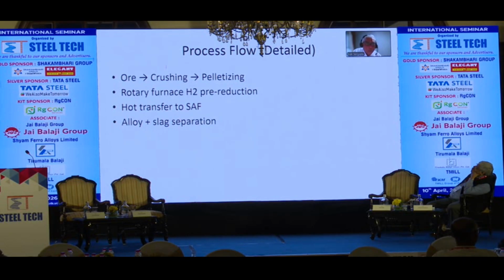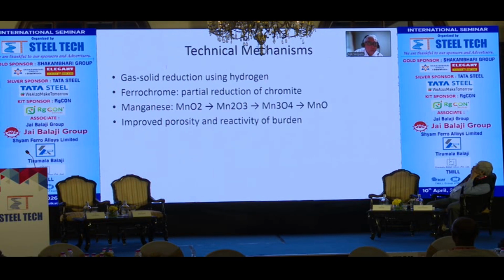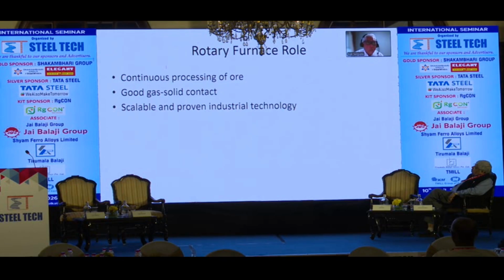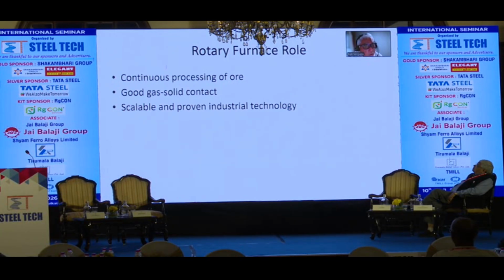So we do the ore crushing and pelletizing, put it into a rotary furnace with hydrogen pre-reduction, then hot transfer to the SAF, with alloy and slag separation. The technical mechanisms are gas-solid reduction using hydrogen, ferrochrome partial reduction, and improved porosity and reactivity of the burden. The rotary furnace role here is continuous. We selected the rotary furnace for the simple reason that it is a continuous processing affair. It has good gas-solid contact, and it is a scalable and proven industrial technology.